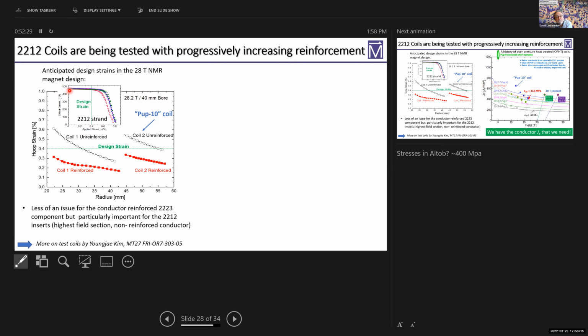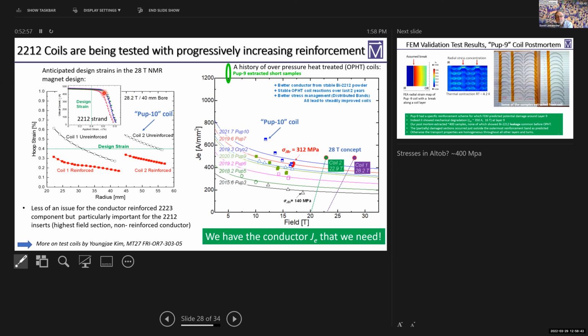Now, one of my colleagues does very detailed strain critical current measurements. And so what you can see here, in the strain critical current, is that you start to damage at a strain, actually, if you look really very closely, at about 0.4% strain. But you can see that this is very progressive, so 0.6%. So these are not materials that fracture catastrophically. And so this is what has enabled us to design some interesting magnets.